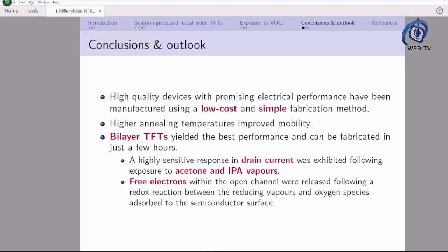As a proof of concept study, tin oxide thin film transistors exhibited a highly sensitive and time-dependent response when exposed to acetone. Following on from that, heterostructure or bilayer ZTO TFTs were exposed to acetone and another reducing vapor, IPA, and the results supported these initial findings.